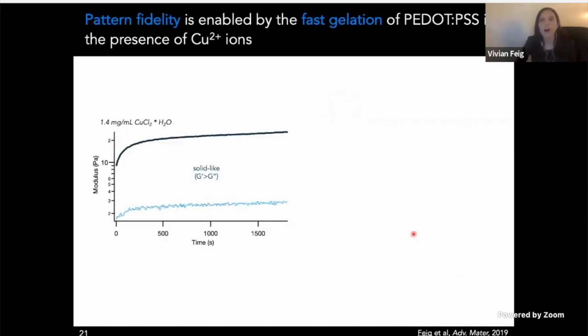One of the really important things that we observed here was that in the presence of copper 2+, PEDOT:PSS gelation happened pretty much instantaneously. So this is the same type of measurement that I showed before with the ionic liquid, where we were trying to monitor gelation time. But here, because it's so rapid, the moment we start taking the measurement, you're already having this solid-like behavior with storage modulus exceeding loss modulus. And so we think that in the case of this patterning method, fast gelation is actually really beneficial because it enables us to retain the fidelity of the original sacrificial pattern, since those ions don't have enough time to migrate from the surface before the gel is formed.